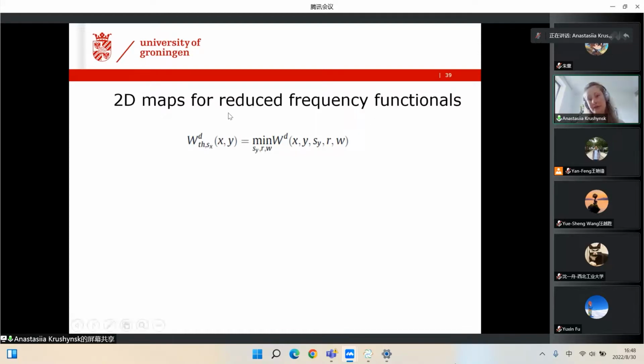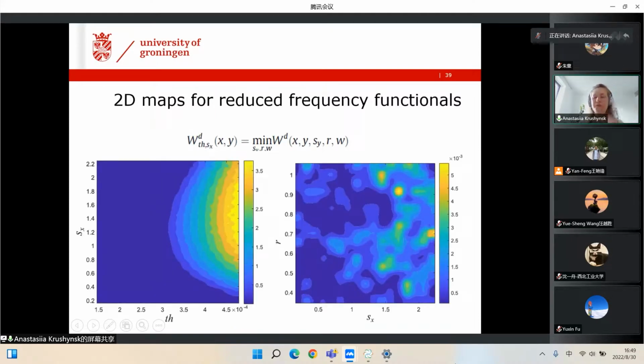And for that, we developed so-called reduced frequency functionals. So we took our functional obtained from the previous machine learning step, which depends on 5 parameters, and chose arbitrary 2 of them. So for example, in this case, thickness and scaling ratio, and calculated the minimum of this functional in terms of the other 3 parameters. This allowed us to construct 2D maps for this 2-parameter function. And we did it for every pair of parameters. So we obtained many different 2D maps.